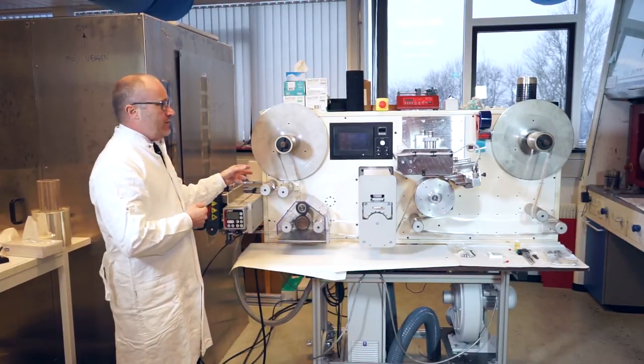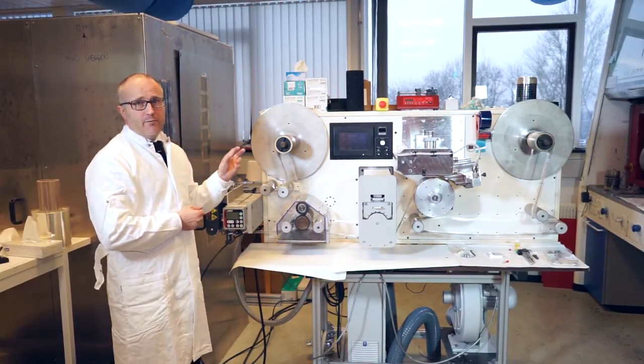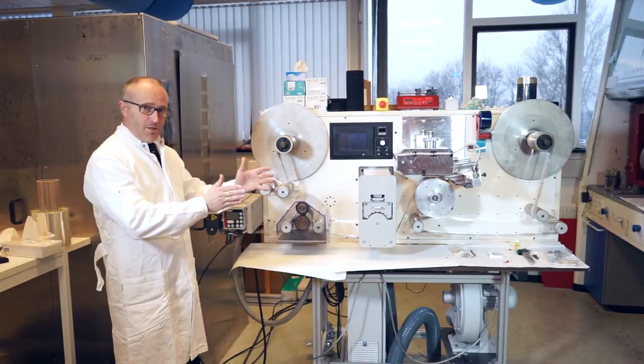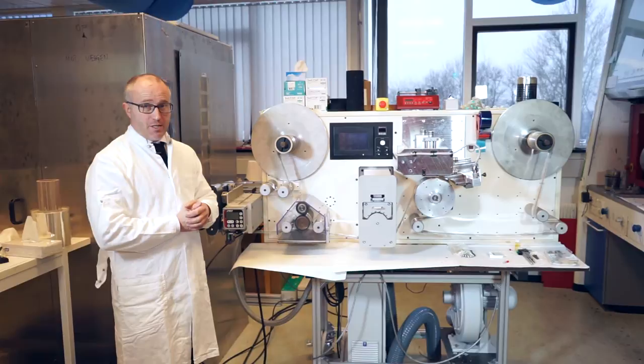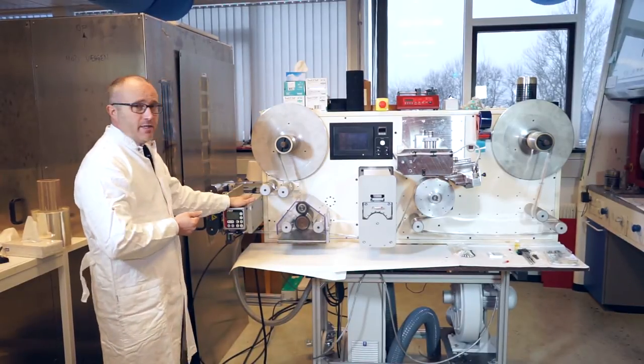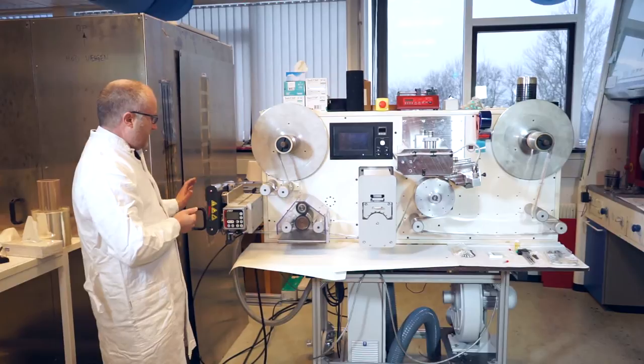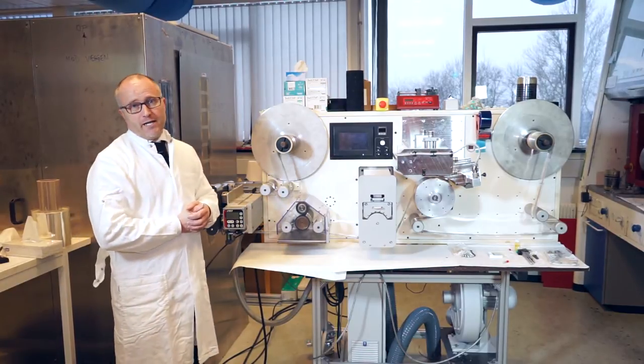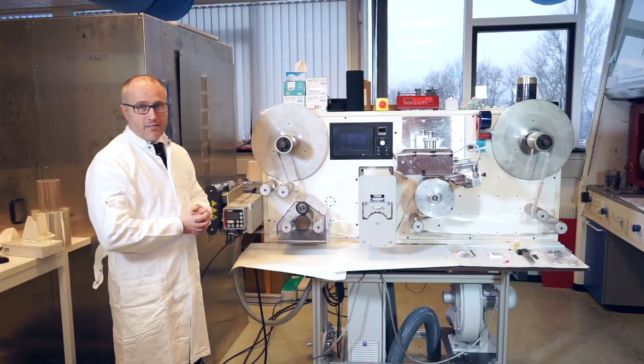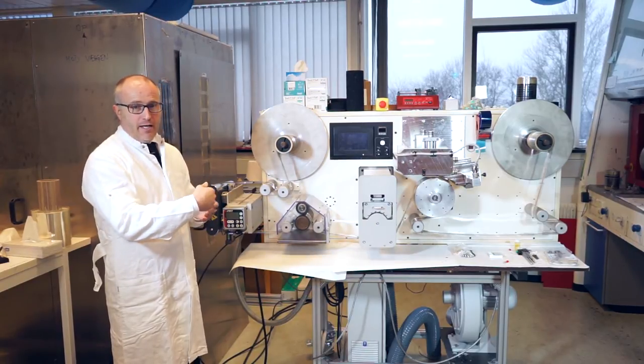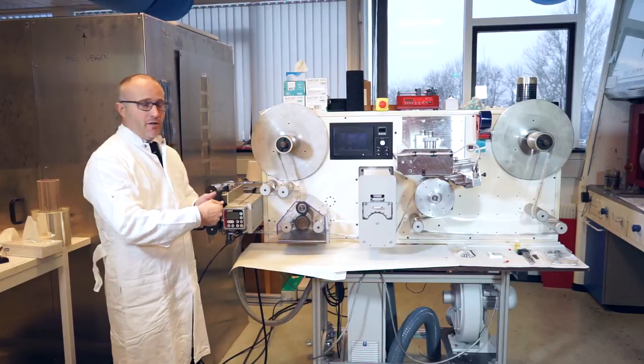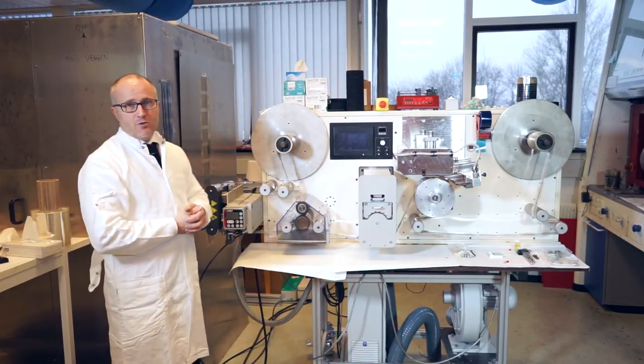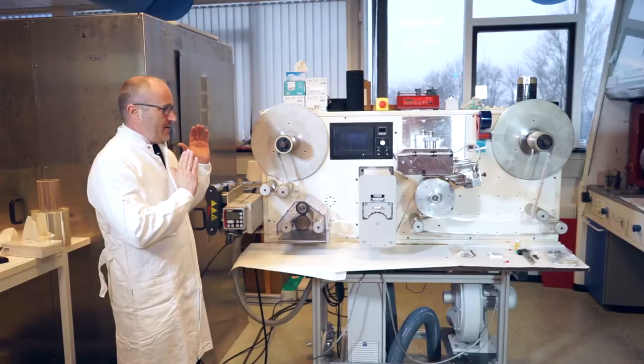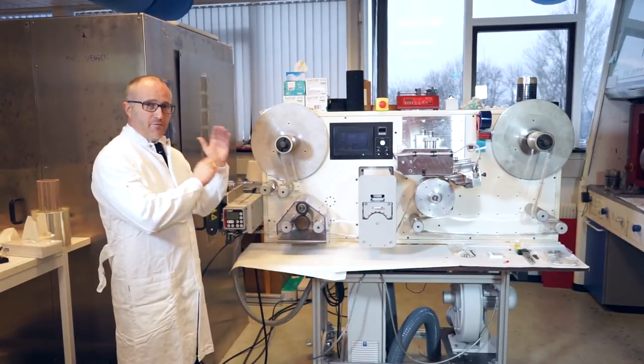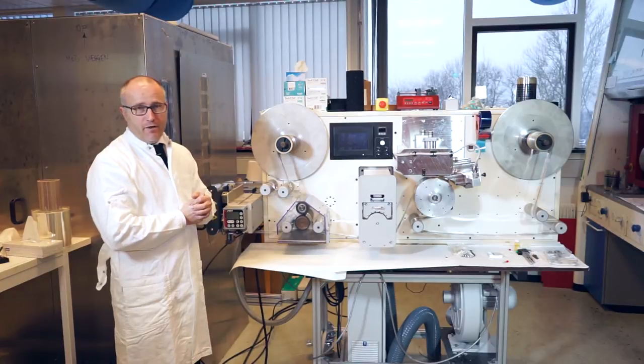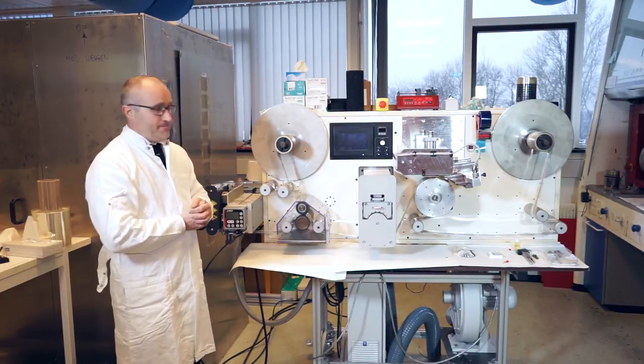First of all, when you have foil running through a machine, you have to be able to control the way the foil runs over rollers. There's no guarantee that it will run straight. Therefore, first thing is you need an edge guide. So it's a set of rollers that can twist and control the direction of the foil. And there's typically an ultrasonic sensor that senses the edge of the foil. And if it moves to one side or the other, this platform rotates to counteract this. And that way you can have foil running straight through the machine. And this is of course important for registration of your printed film.